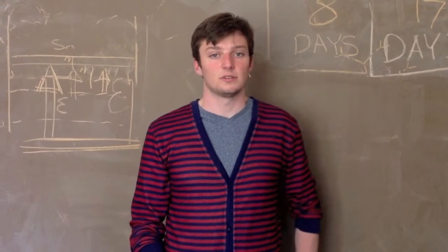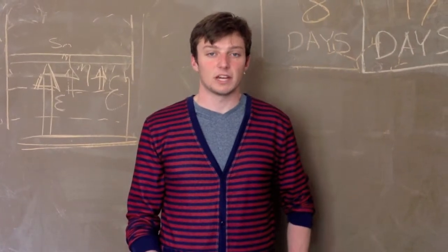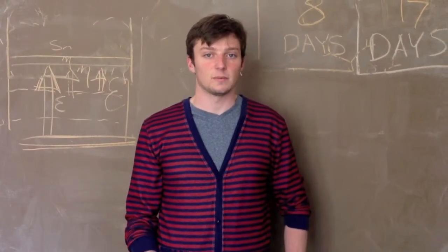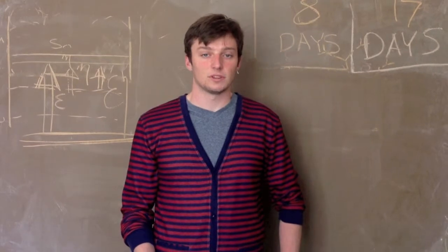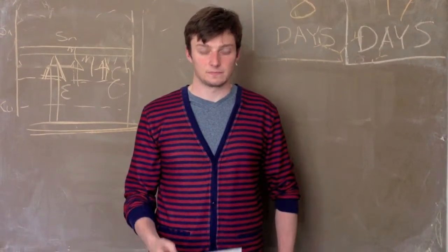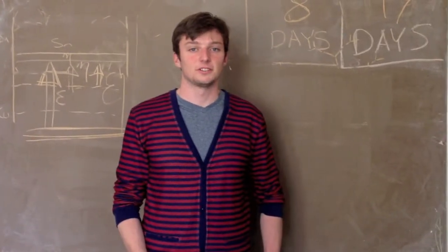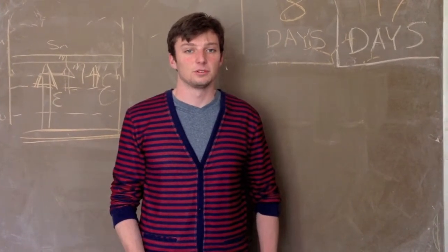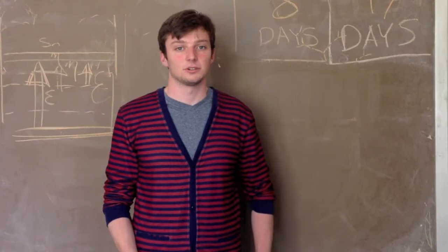Tin has a high sodium alloying capacity with a maximum of 3.75 sodium atoms per tin atom, with a theoretical capacity of about 850 milliamp hours per gram. Unfortunately, tin experiences large volume cycling that pulverizes the anode and ultimately restricts capacity.